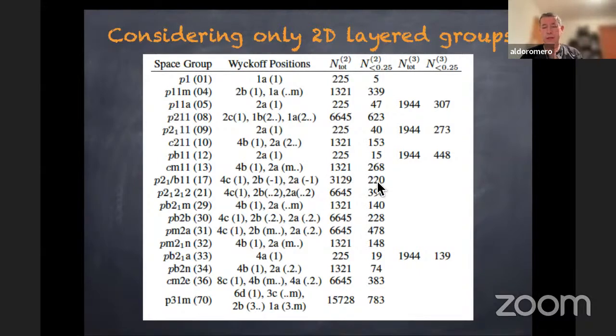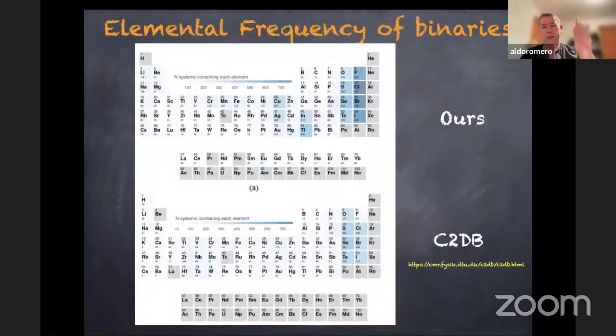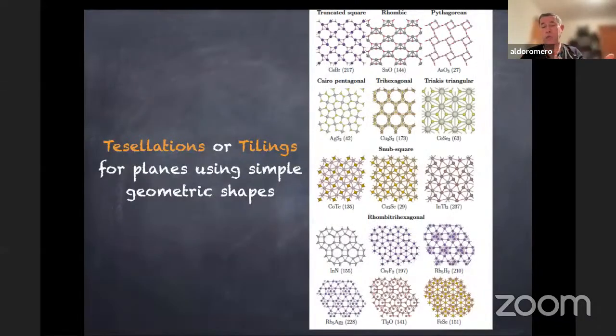And from those, 220 are chemically stable, which are 0.25 with respect to the convex hull. We compare, for example, the database that we have created with the most accurate one that exists, created by a group in Denmark. The number of structures that they have reported is around 4,000. The one that we have is around 7,000. Therefore, we have 3,000 structures that are not reported in the literature and which are completely new. And we can now see and study the patterns.